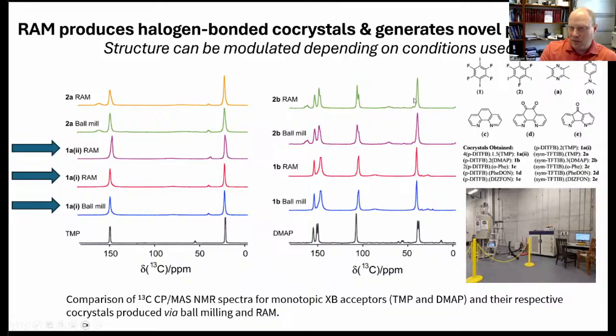So this is more spectra, carbon-13 spectra now of the same types of co-crystals. And this is a tetramethylpyrazine carbon-13 spectrum at the bottom left. We prepare co-crystal 1A. We get this trace with ball milling and with RAM, same product. In this particular case, we have a second polymorph 1A2 prepared with the addition of a small amount of solvent. And you can see there's actually a small shift in these peaks, indicating that we're able to get a different polymorph now with RAM by adjusting the conditions used, a polymorph that we're not able to get from ball milling.